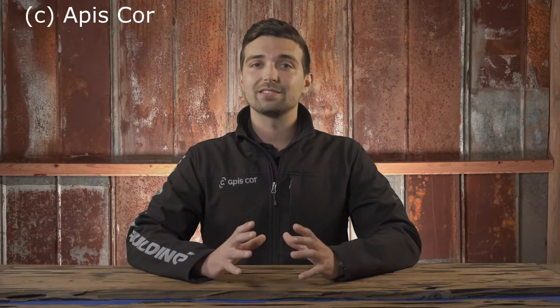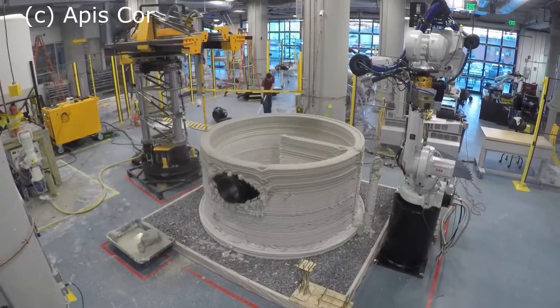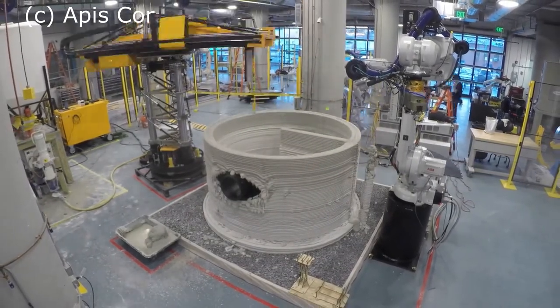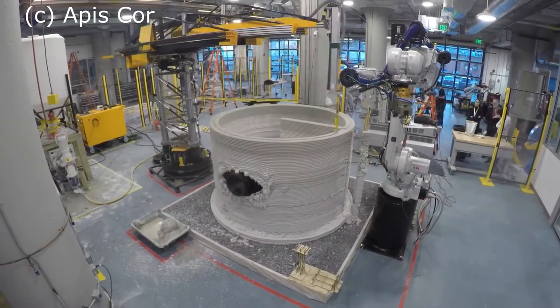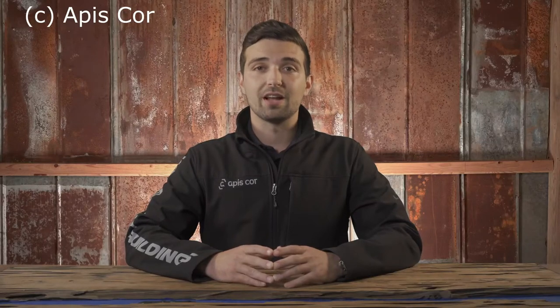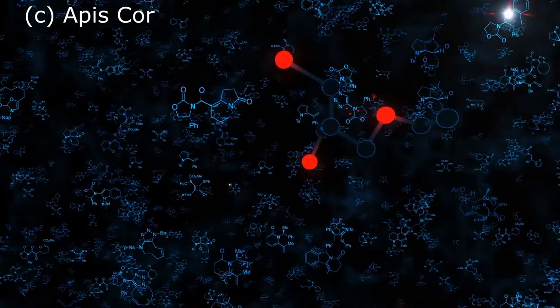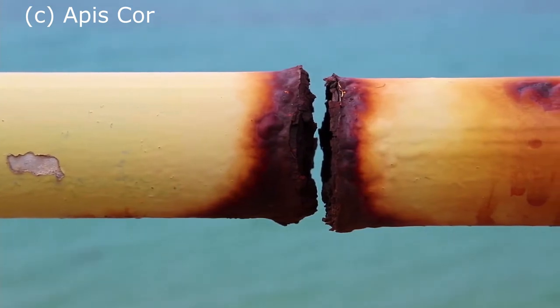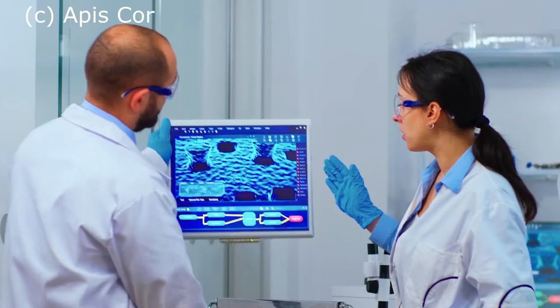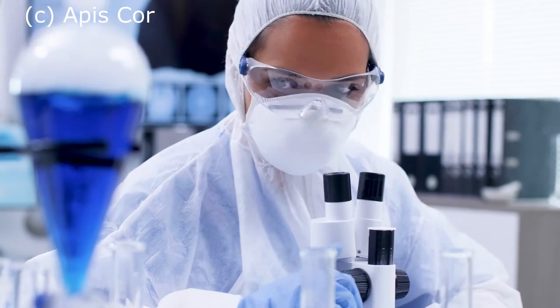The rate at which setting occurs can be controlled by another type of admixture called accelerants or accelerators. These accelerants are a catalyst that speeds up the chemical process of hydration, thereby causing the curing period to begin sooner. Most all 3D printed mortars contain some form of accelerant, but the type and ratio of accelerants used can be adjusted for better performance in more extreme climates, for different extrusion rates, and even for different types of architectural forms. However, some accelerants can cause cracking and weaken the integrity of cured 3D print material, and others can even release chemicals that can corrode steel and damage the reinforcement within the 3D printed wall system. It's even possible for some accelerants that would otherwise perform well to have an adverse reaction with a completely different admixture, which can have unintended consequences that weaken the integrity of the 3D printed wall system.